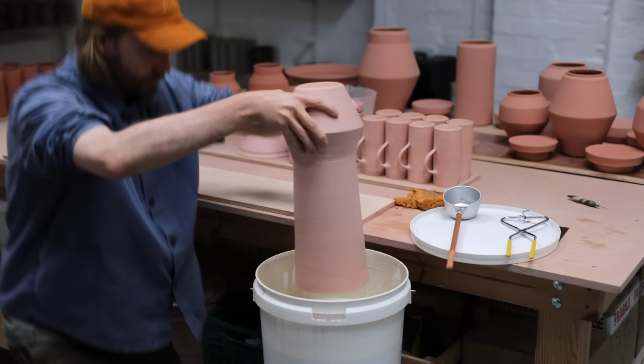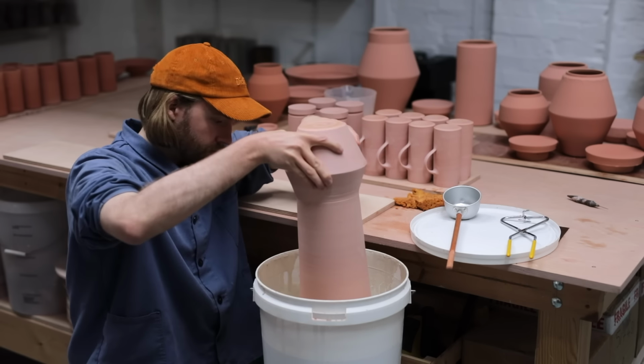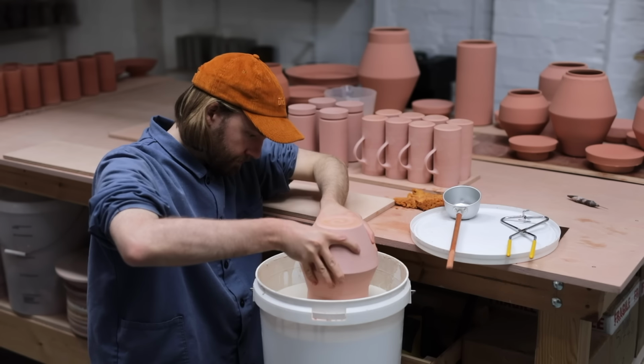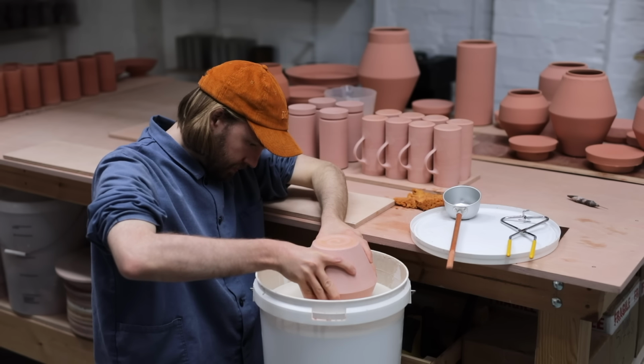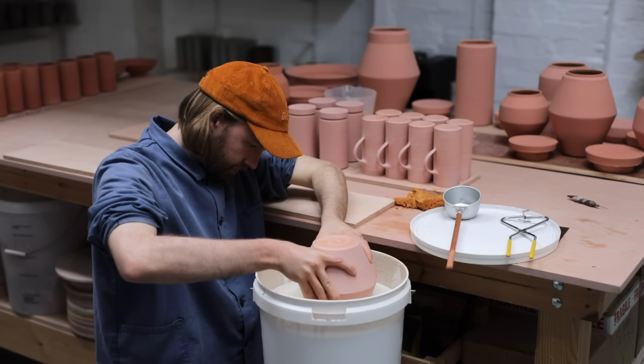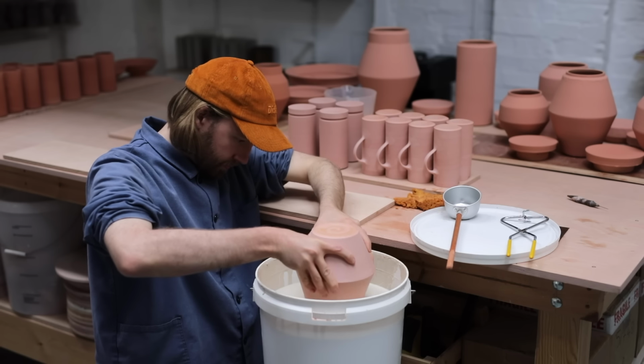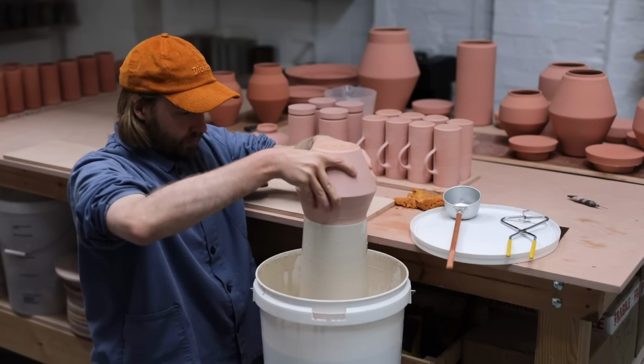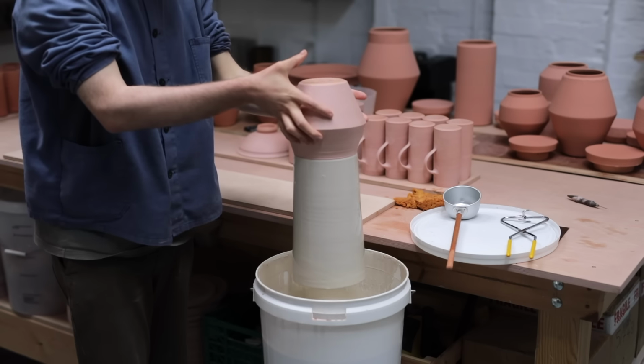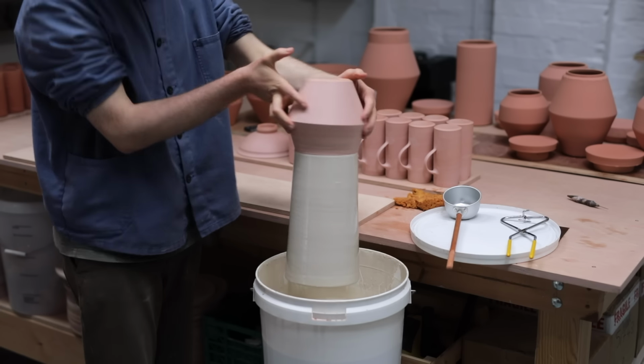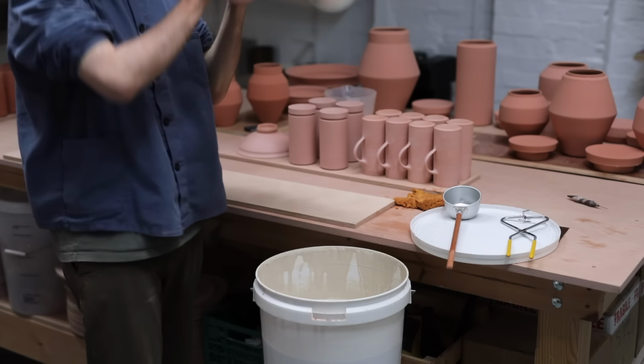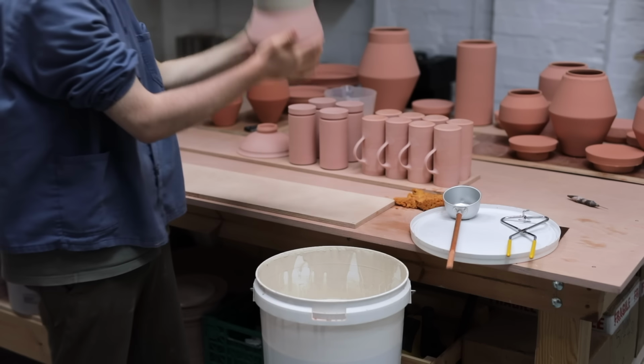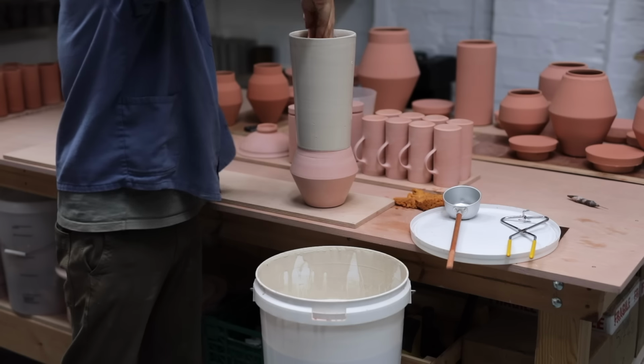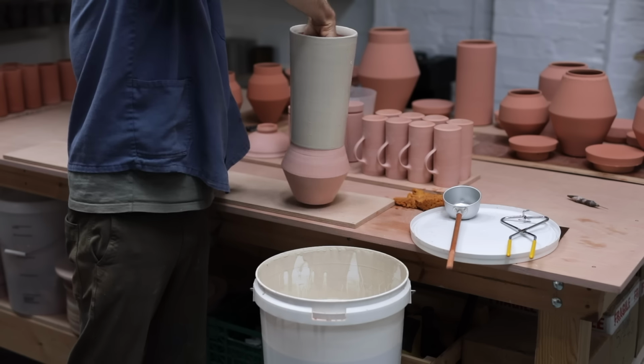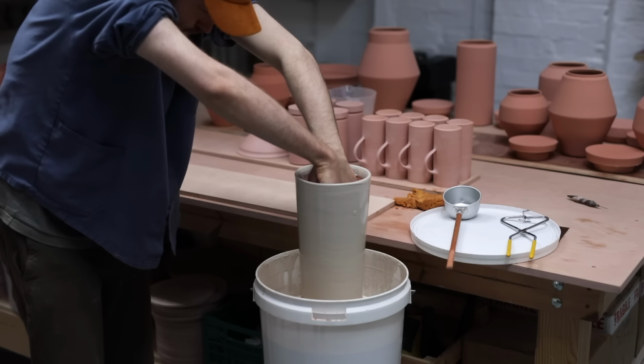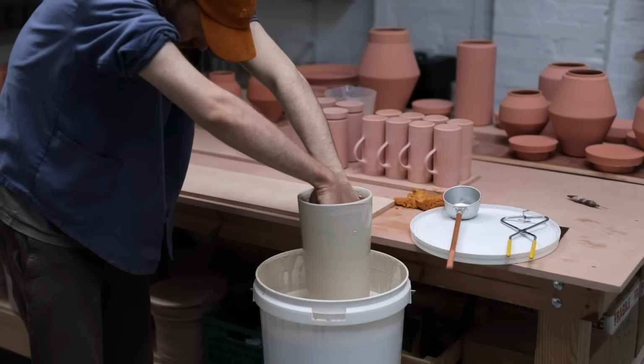You might not think that 2% iron would make much of a difference, but not only does it alter the colour considerably, but the glaze itself also coats the pots in a much nicer, more even layer. I call this a white glaze due to how stark it is at the moment, but after being reduction fired, it's more of a grey tone, and all of the variants will be speckled with dots of iron which are pulled out from the clay body itself during the firing process. And once again, I dip the top first, then place my hands inside and push out horizontally, and then I dunk the lower section of the vase.